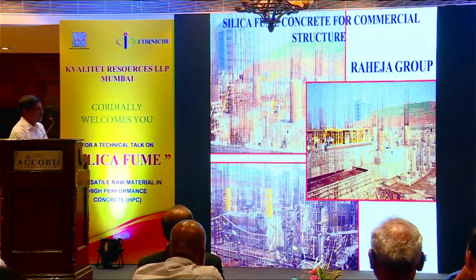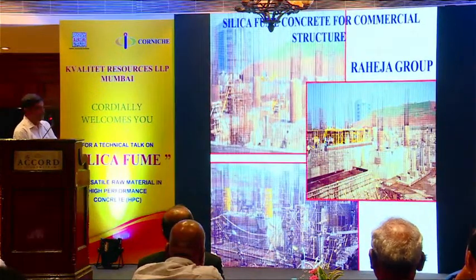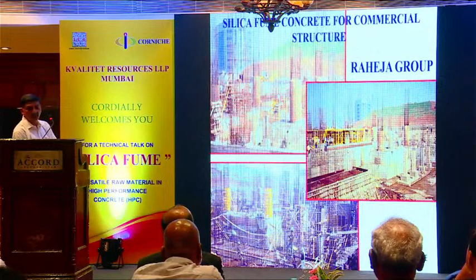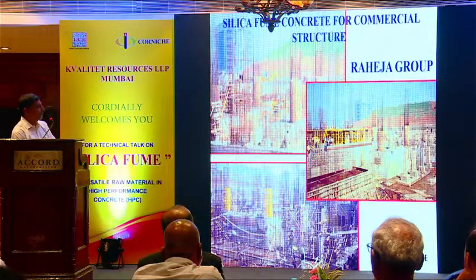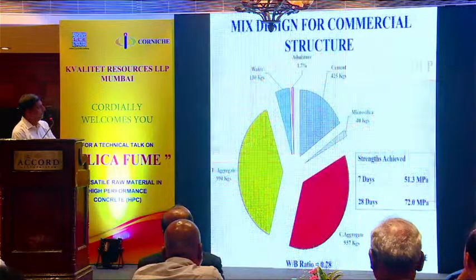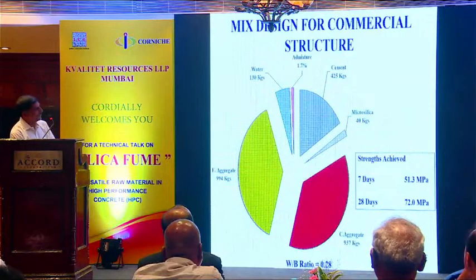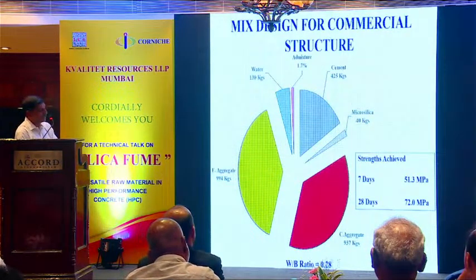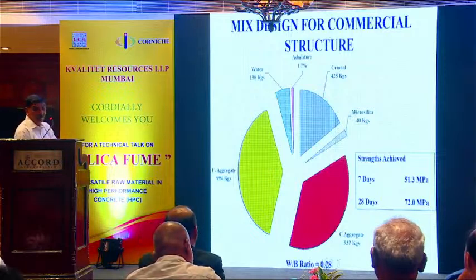One of the first high-rise buildings in Mumbai in the mid-90s, Raheja, on the western side, Kandivali. They specified M60 for columns, a residential tower. Look at the mix, 425 kg cement, 40 kg of silica fume. In 28 days, they were hitting 72 megapascals. And water binder ratio, 0.28.